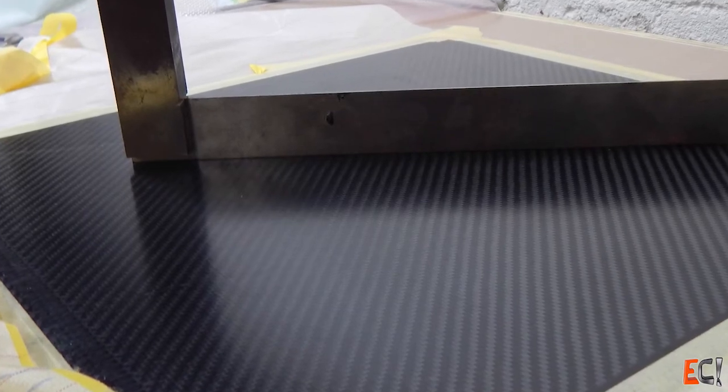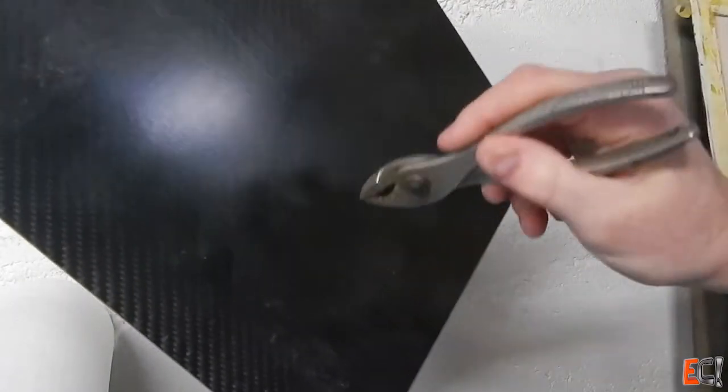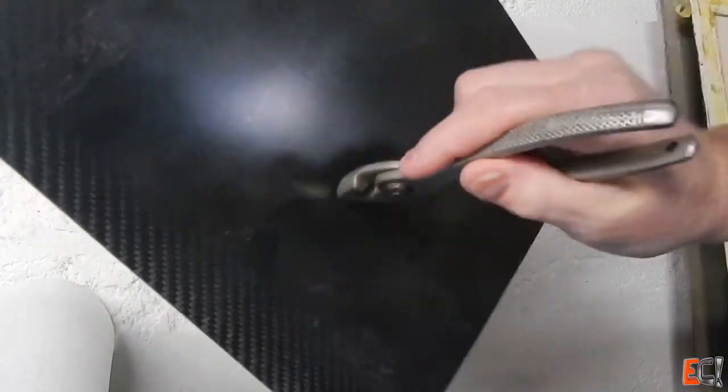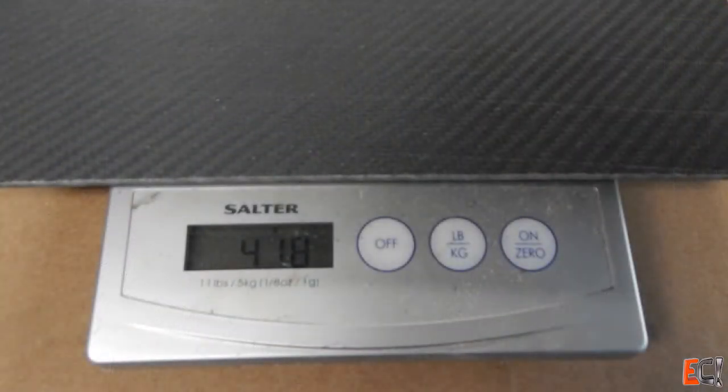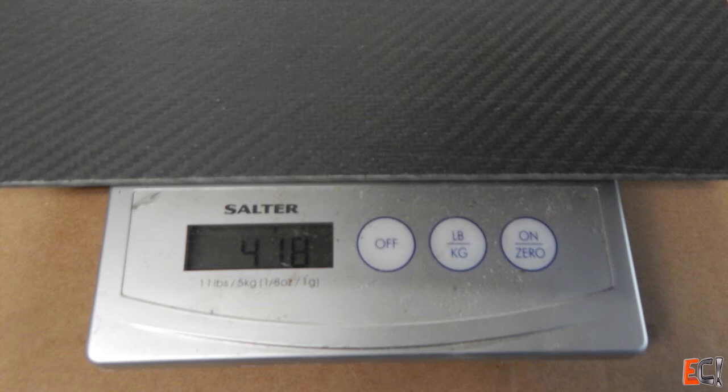And balanced there were not a lot of stresses built in and it did come out right about exactly 3 millimeters. And the weight 418 grams which was just a little bit more than the 410 grams that our estimate predicted if you look back at the beginning and I'll show that again now.